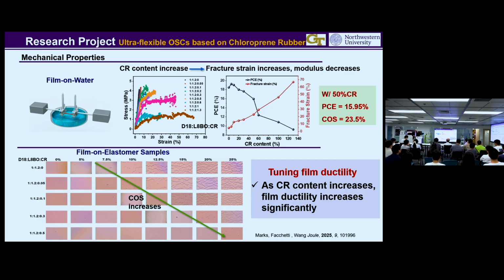And so now we're going to look at mechanical properties. And what's amazing is you can add up to 50 weight percent chloroprene, and the PCE goes down only a little bit. And this is called the cracking onset, which is about 25%. So as you add the chloroprene, it gets more and more stretchable.